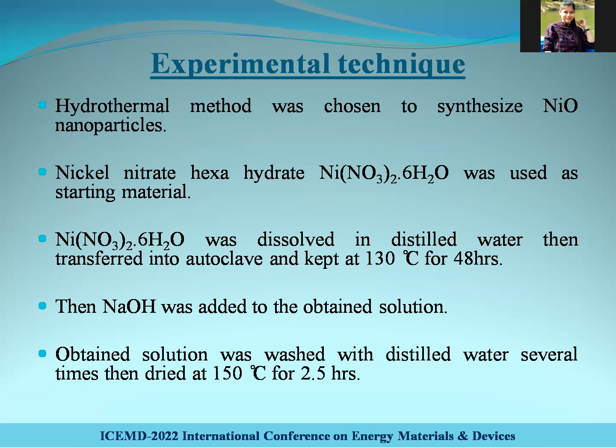Now this is the experimental technique which I have done. I have taken nickel nitrate hexahydrate as a starting material, and this was dissolved in distilled water, then transferred into an autoclave, and the solution was kept there at 130 degrees centigrade for 48 hours. And after 48 hours, the solution which we obtained from the autoclave,